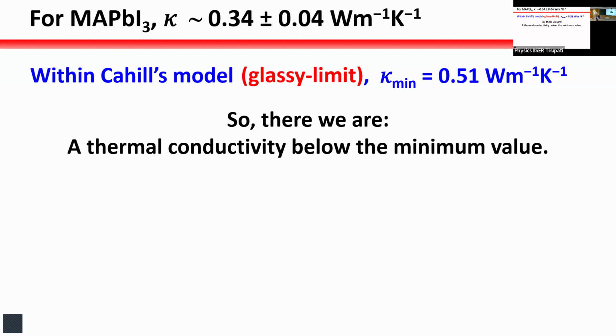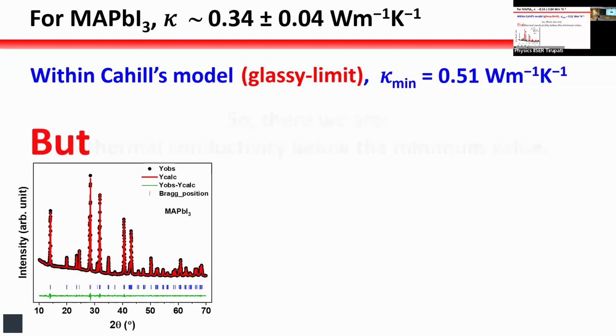It just cannot happen. I mean, we are talking about the glass limit. Is this material glassy at all? If you look at its X-ray diffraction, it has such sharp peaks, there's nothing glassy about it. And yet the thermal conductivity is lower than the glass limit, saying that there's absolutely nothing ordered about this material. This happened. And what is this value? Where is this coming from? Not this one, this is even 40% lower than that.